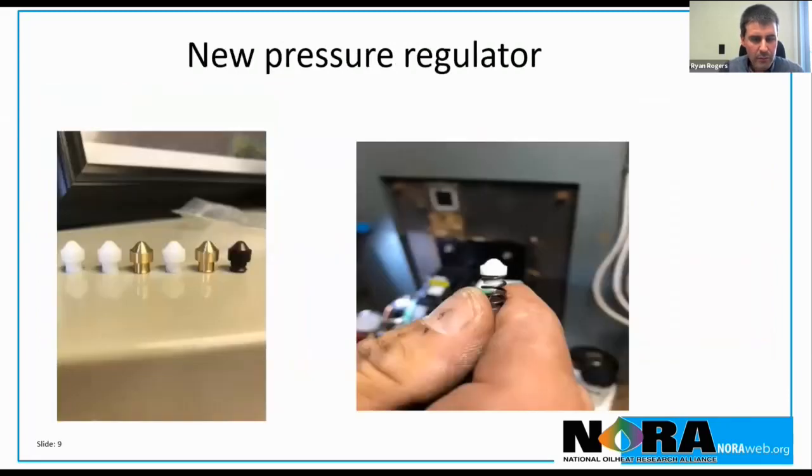So one of the main issues with the pump that we had was the pressure regulator. In the picture on the right, the furthest right is what the Beckett Danfoss comes with, that pressure regulator, and you can see the Teflon and brass pieces that a friend of mine machined. That little piece of nitrile would swell and close the oil off, and we'd have a flame failure.